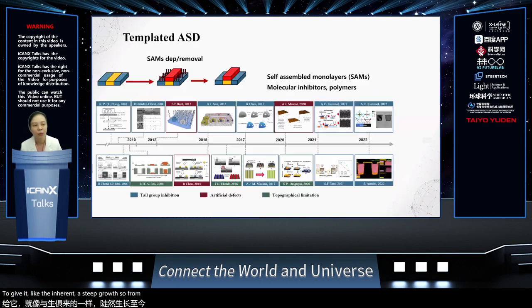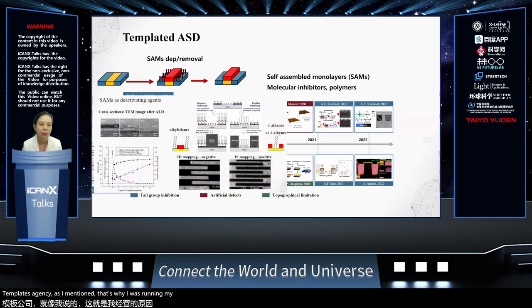So from that, I'm starting to talk a little bit about templated ASD. As I mentioned, when I was doing my PhD, we were studying the effect of this kind of self-assembled monolayer. Either they grow on oxide or they grow on hydride. And we investigated the chain length, the time, and everything in order to achieve complete deactivation.